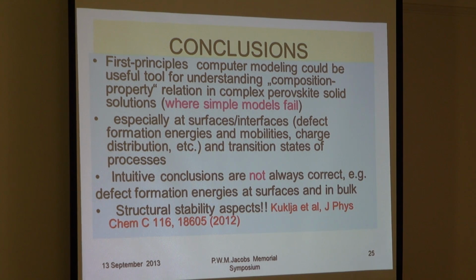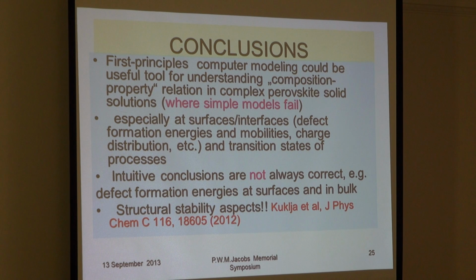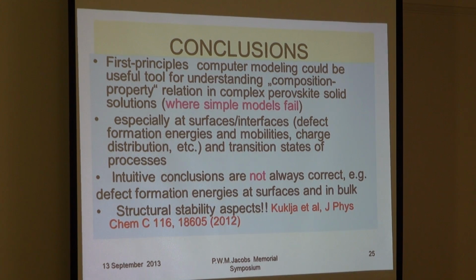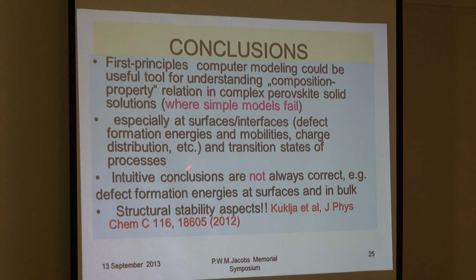as I mentioned, these materials like BSCF are the most efficient for oxygen reduction processes, but it was discovered recently that they're unstable with respect to the transformation from the cubic phase to the hexagonal phase. When temperature is decreased a little bit from the operational one, and when it's in the hexagonal phase, its properties are essentially lost. So the materials are unstable with respect to transformation, and essentially what we are working on now is, again in the spirit of Patrick's interest in decomposition processes, another illustration of these problems. We study structural instability of these materials, and this is just another story published in a recent paper.